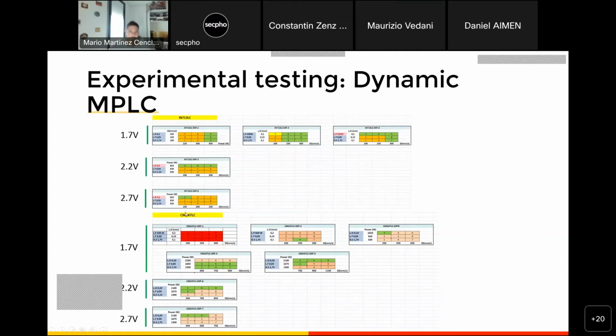And on the bottom, you can see the same for the CM247 low carbon. So we have followed different approaches. In the case of the Inconel 713, we have played with very low powers, as you can see here, 200 watts, 400 watts. We have increased the laser power slightly when using these other configurations because the primary beam has less energy. But in general, we used very low powers and very low scanning speeds, as you can see here. So these are very low scanning speeds for the PBF process.